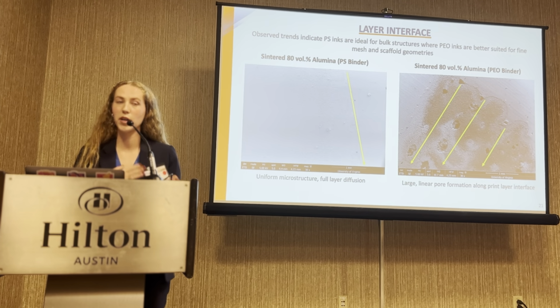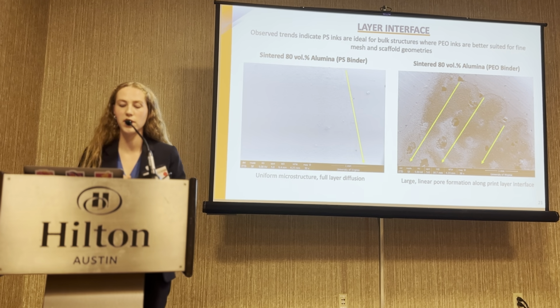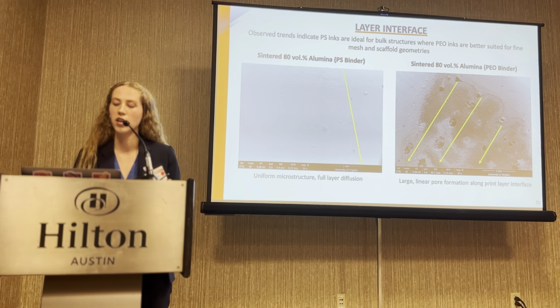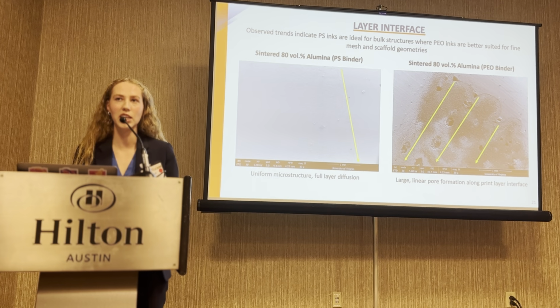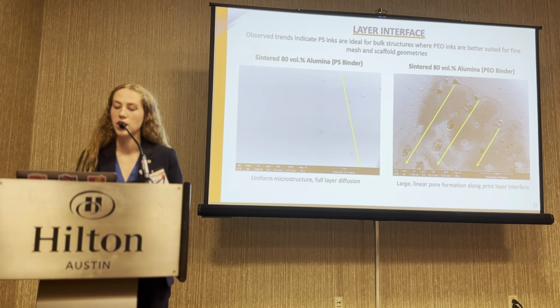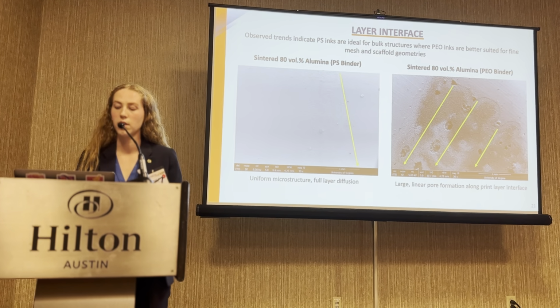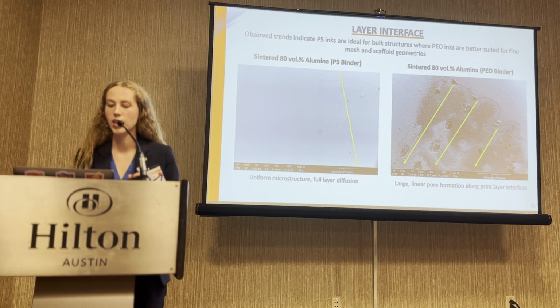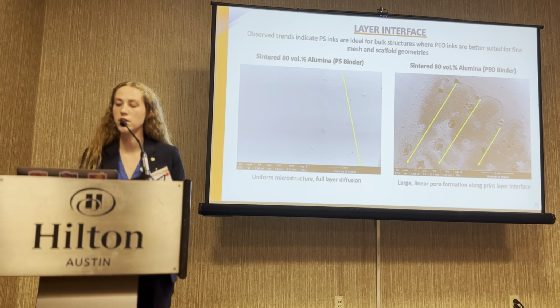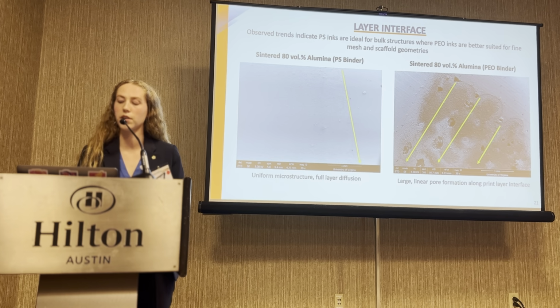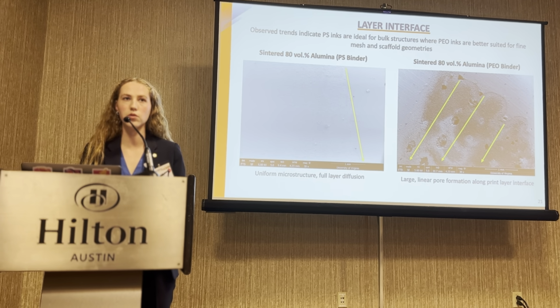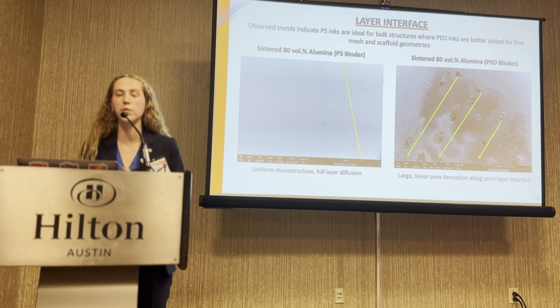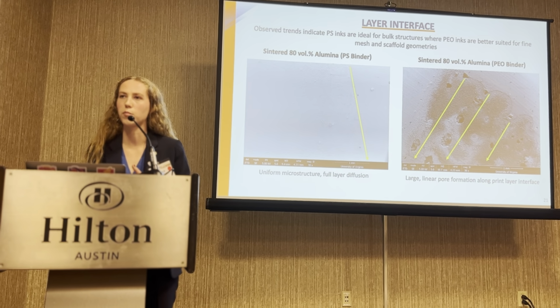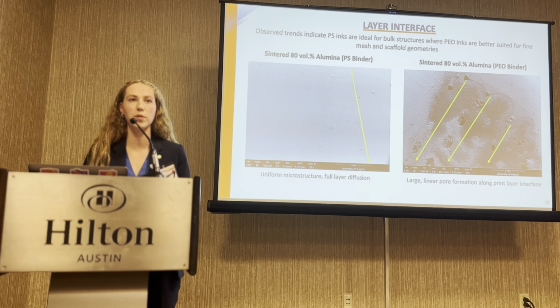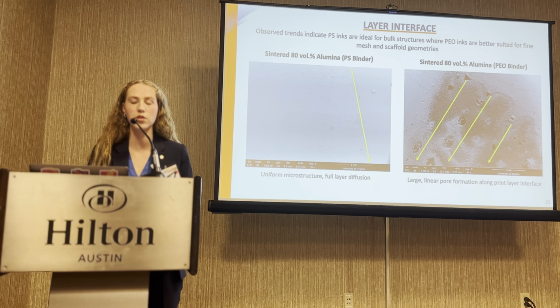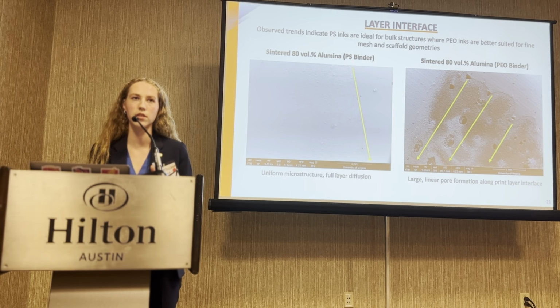And on a more microstructure level, from the layer interface, we observed that the polystyrene binder is essentially indistinguishable with the layer boundaries as complete diffusion in the sintered part. PEO, being the bigger polymer, keeps solvents from diffusing through the layers effectively, so it creates more of those bubbles on the layer boundaries. Those fusing issues occur more in bulk structures, which is why we recommended polystyrene more for bulk parts. However, we're doing additional work to mitigate those fusing issues in the PEO with the addition of a plasticizer.